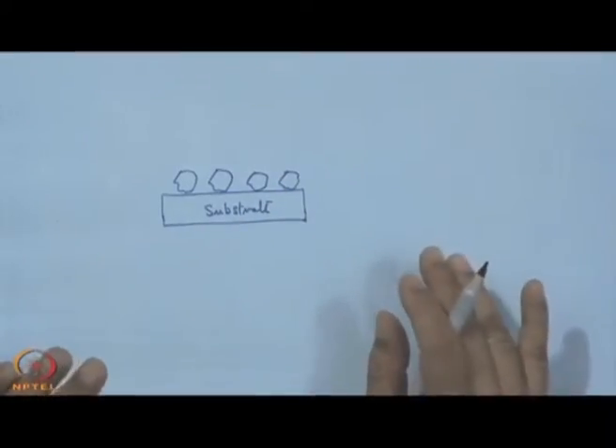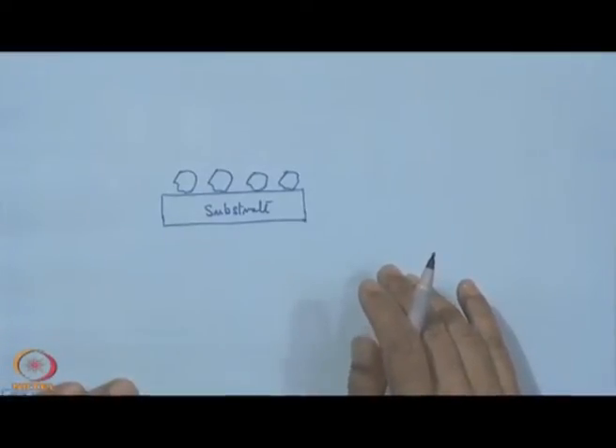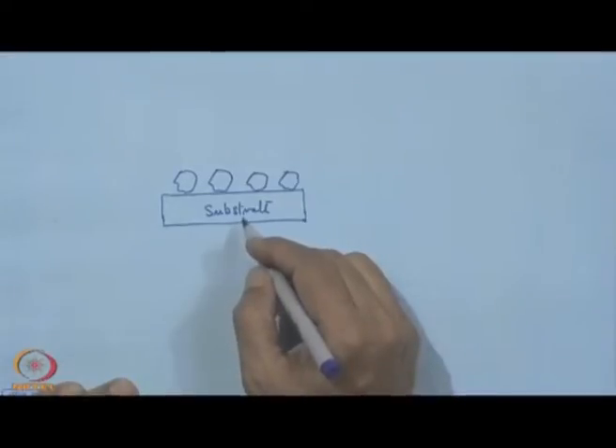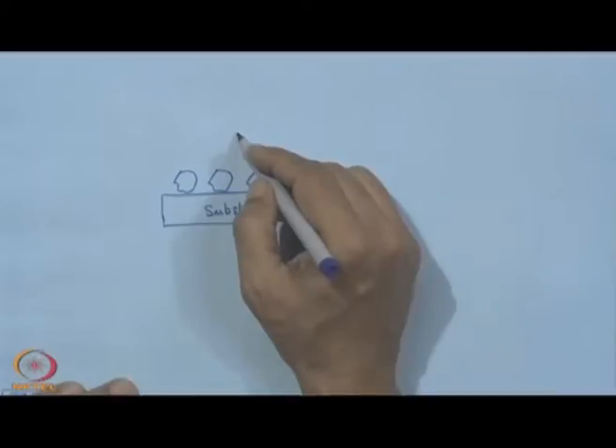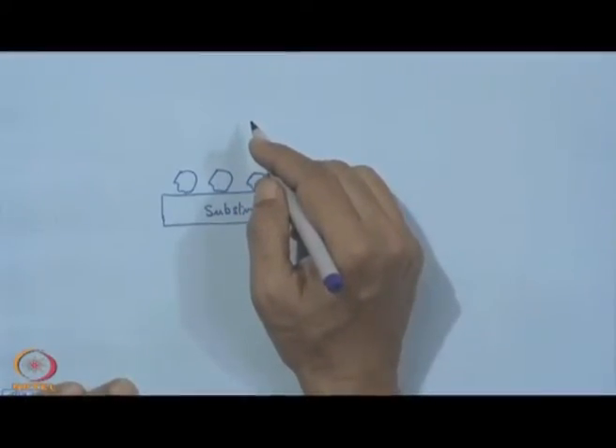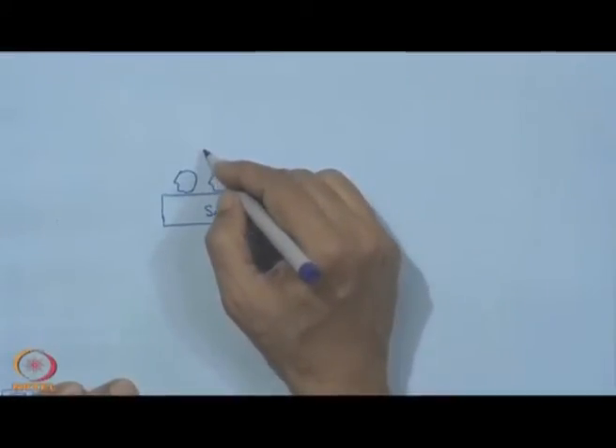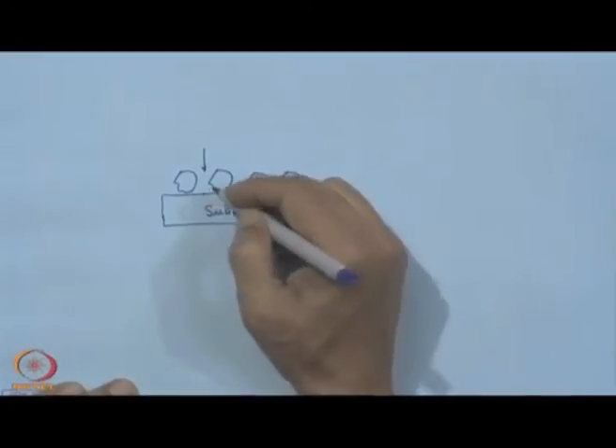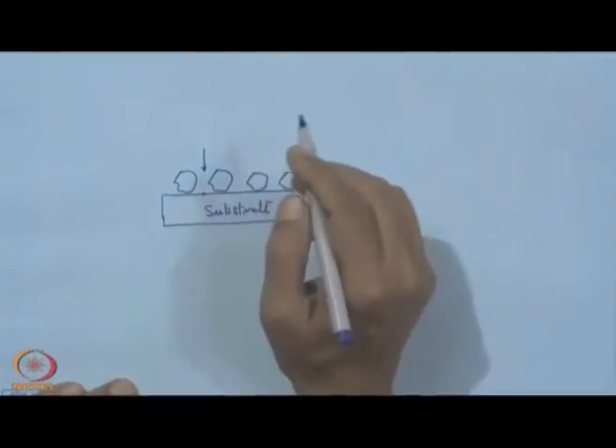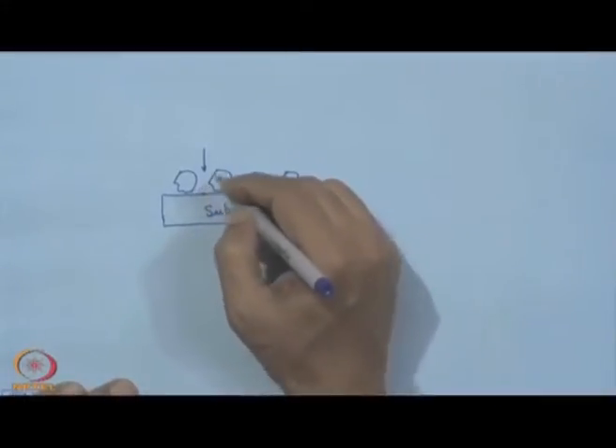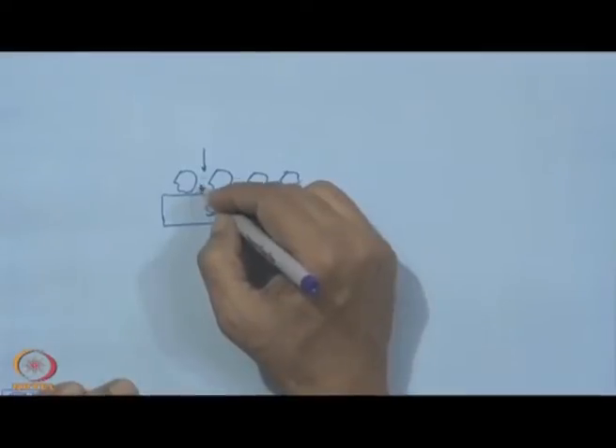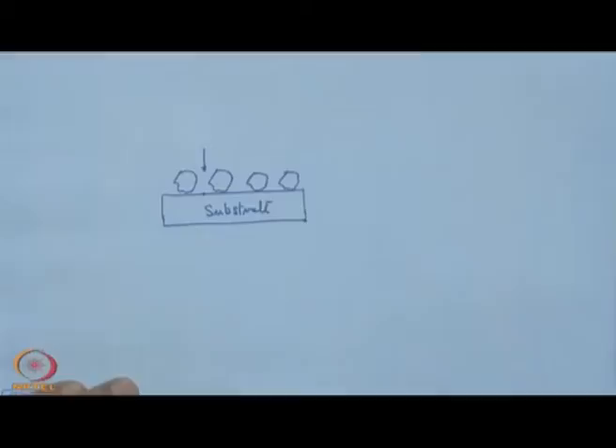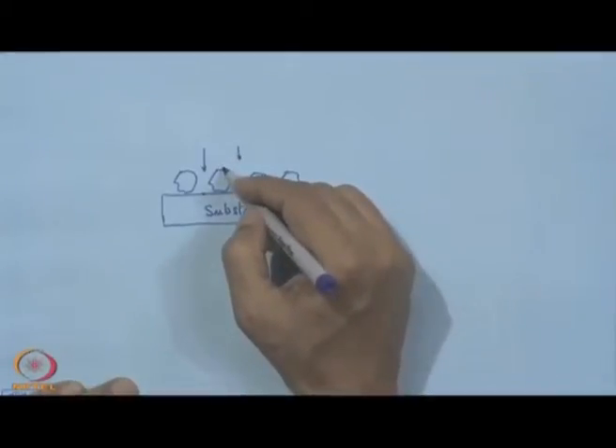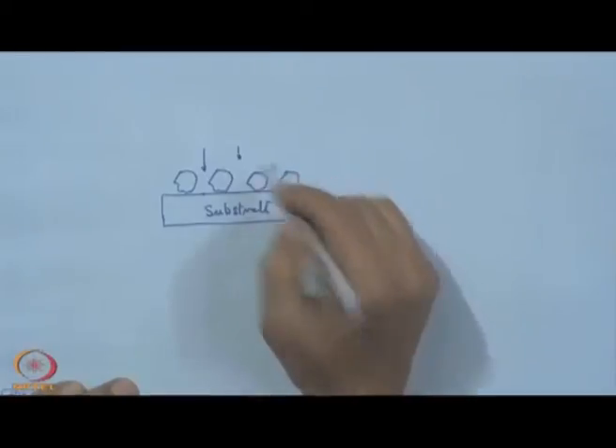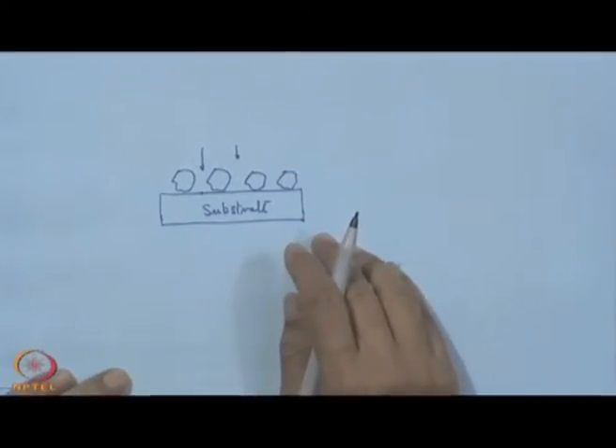So, this is the arrangement one has to make, and then what happens? This will be electrically polarized, and the metal ions produced during this electrolysis and electrochemical reaction will be attracted to this side of the substrate, where they will be neutralized and become metallic in nature, and this metal will build up around the grit. It should be reminded in clear terms that not even a single particle of this electro deposited material should be collected on the grit surface, otherwise the whole purpose of electroplating is lost.